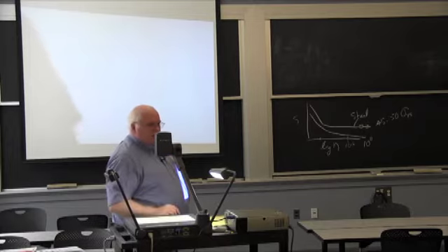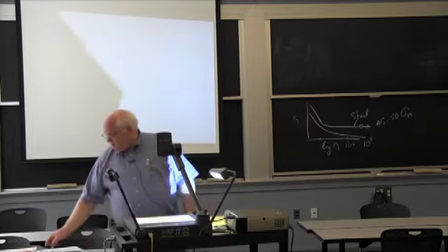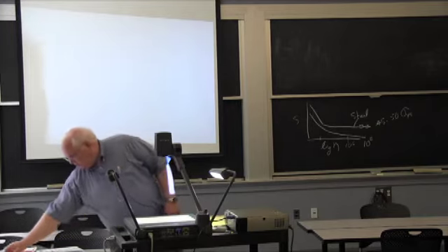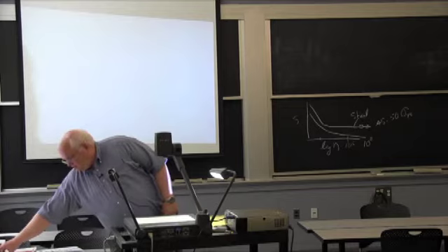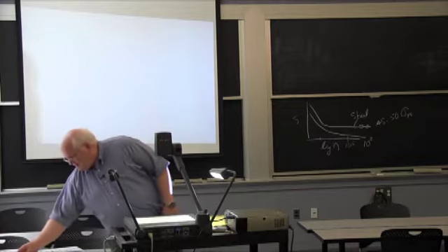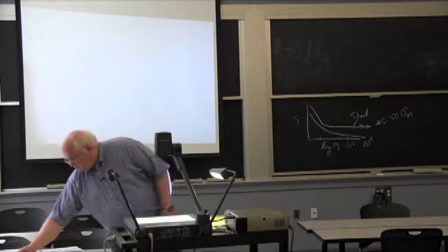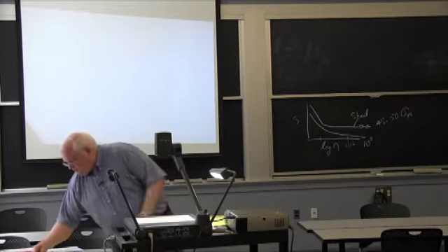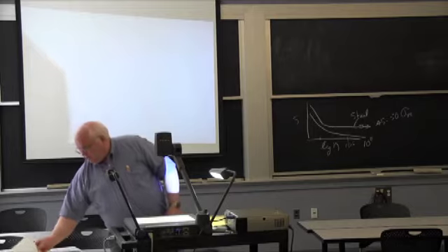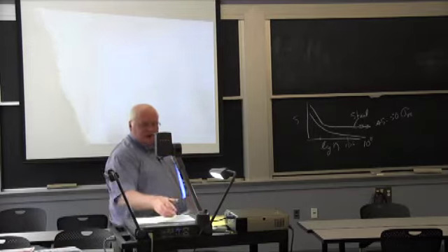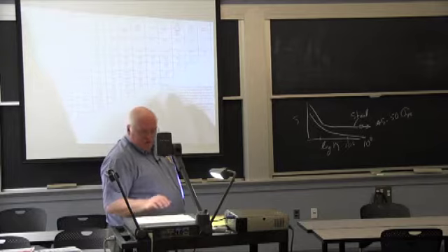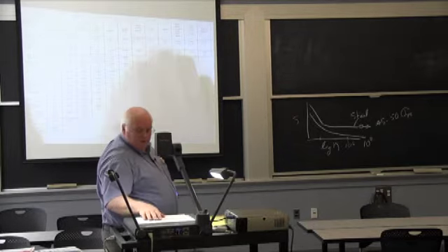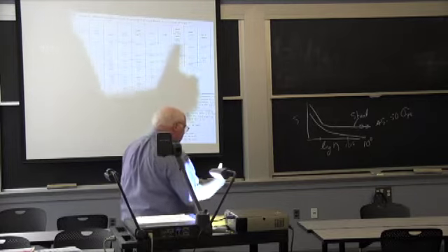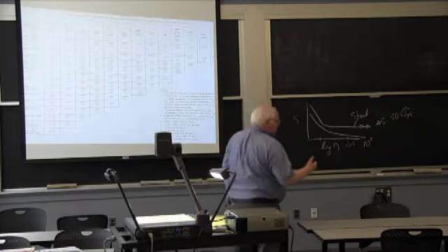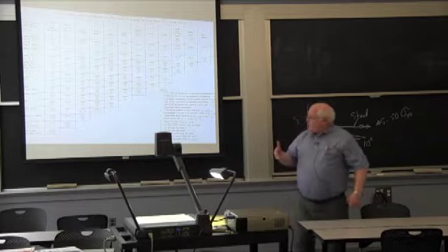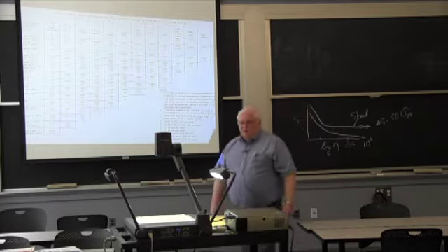There's one in Australia that was a big surprise about 50, 60 years ago to the designers of steel. And a lot of those details that I just showed you come exactly out of the steel construction manual in terms of weld type details, but they apply to aluminum in a lot more complex ways. Aluminum doesn't have the strength of steel. It's got about 1/3 the strength of steel. I mean, you can get 60, 70 KSI yield aluminum alloys, which are heat-treated aerospace alloys that are not very weldable.